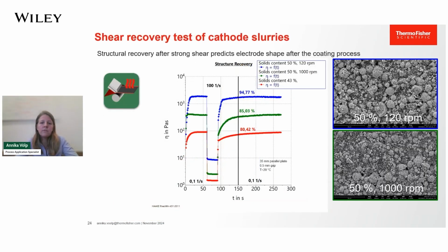Thixotropy of slurries predicts their coating stability and can be characterized by shear recovery tests. The slurries are sheared with a small shear rate at 0.1 reciprocal seconds until a steady viscosity is measured. Subsequently, the slurries are sheared at a high shear rate that mimics the shear rate in the slot die, and then the shear rate is abruptly changed back to the low shear rate.